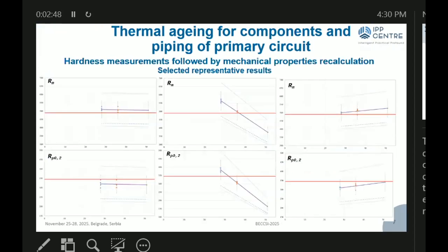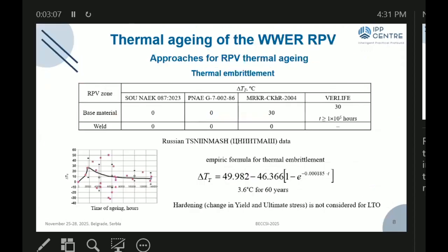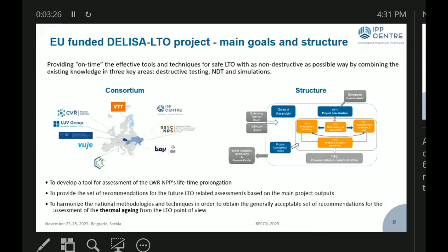This slide shows an example of determining the mechanical properties using hardness values at different years of operation. As you can see, it is impossible to estimate the thermal aging effect. Regulatory documents state that thermal embrittlement is only taken into account for the RPV. According to this document, thermal aging does not affect LTO, long-term operation. Also, thermal aging hasn't been determined yet. It could affect up to 60 years of operation.